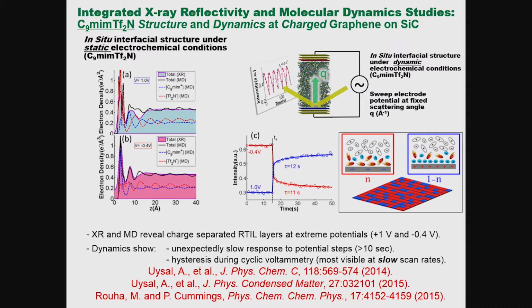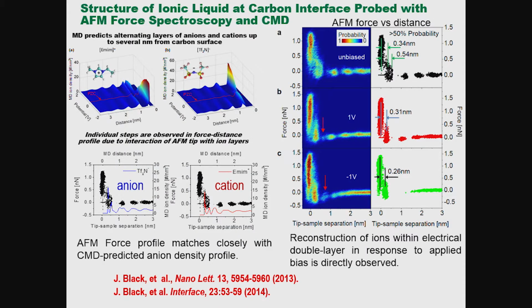The current interpretation, which we're getting from combined X-ray reflectivity and MD modeling, is that the surface consists of a patchwork of cation and anion terminated structures, or local pancake structures of layered ion distributions that simply shift in their relative abundance as one cycles through potential. But as Ahmed showed, even slowing the scan rate down to very low scan rates, this hysteretic behavior of bistability persists, and this is a current topic of great interest in our center.